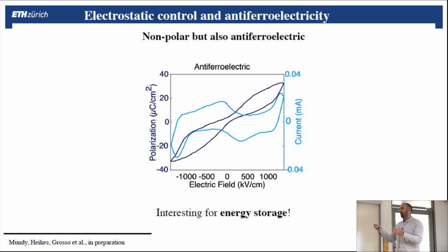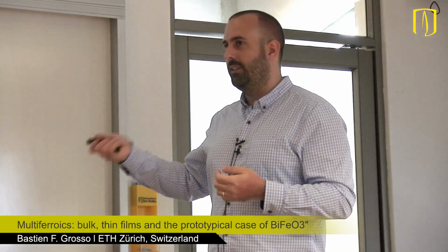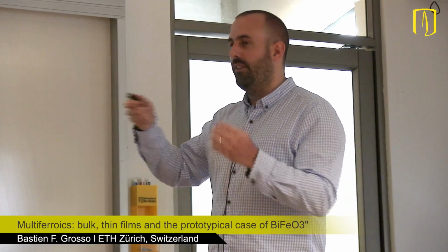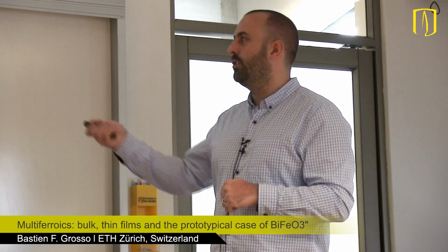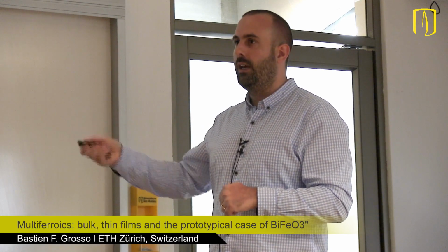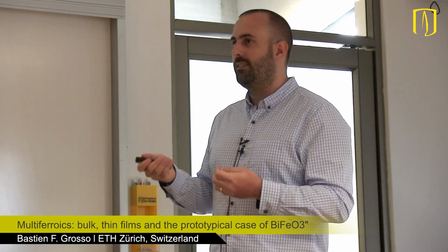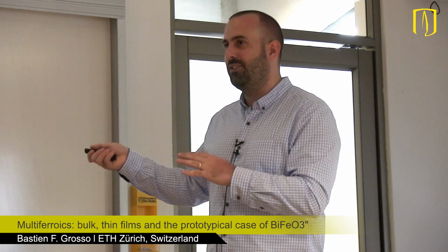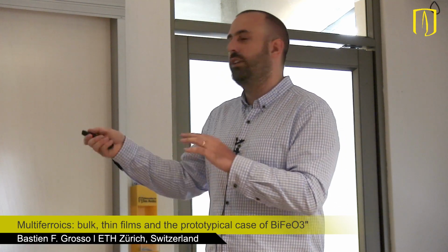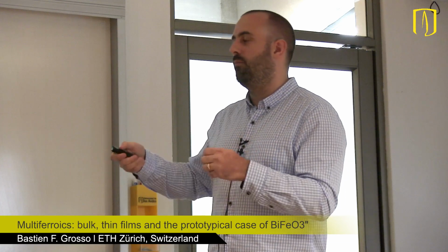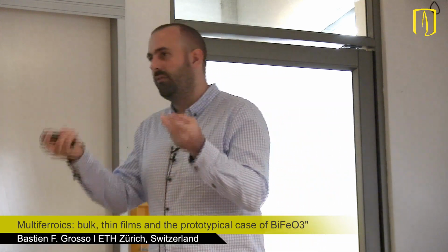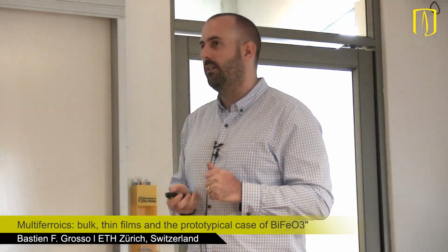So from a multiferroics point of view, that's not so interesting, I would say. Because as I said before, in general, one looks for magnetic, for electric, or at least one of the properties. So that's not what is interesting. And in that case, to have antiferromagnetic and antiferroelectric is interesting only from the antiferroelectric point of view, except if we find that there is an interesting coupling or change in the magnetic order. But let's say on this answer from these results, I would say it's not interesting from a multiferroic point of view, but more from a ferroelectric point of view or antiferroelectric for energy storage.